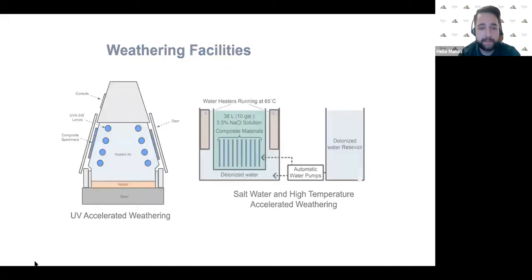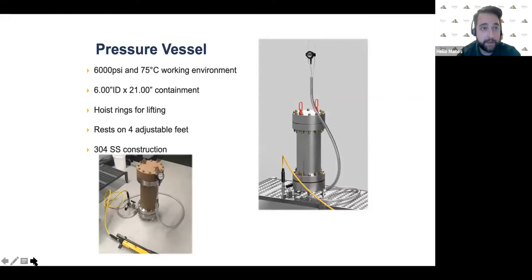And on the next slide, we have another variation of the saltwater weathering facility shown here. We have the same saltwater bath, and this large stainless steel canister, where the specimen sits inside, is pressurized. So now we're introducing another variation that would induce the absorption rate. This way we can get even higher acceleration rates, but still stay below that glass transition temperature. So instead of mimicking 5 to 10 years within a month, depending on the material again, we could mimic something between 10 to 20 years or even higher if we let the material soak in this water for longer.